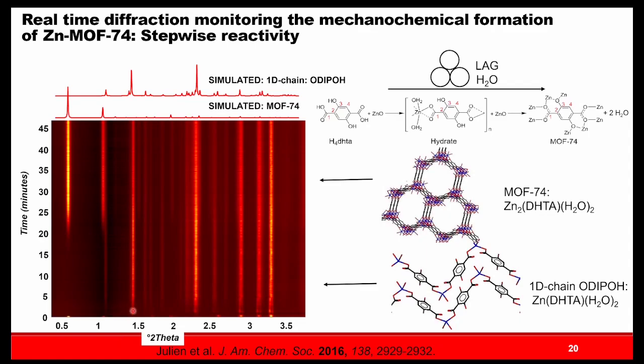And so when we do this in real time, what you're seeing here is the PXRD patterns on top. So this is the simulated pattern from MOF-74. This is the diffraction pattern for this 1D chain polymer, which is reported in the literature. And when we look at the diffraction signal over time, I'm going to show a lot of these waterfall plots, as they're called. And what you're looking at is the time axis goes up here. So we're starting at 0, going to 45 minutes. And this is the 2 theta axis, or the diffraction angle.